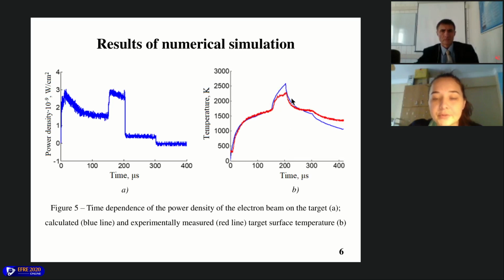There is a difference between the two curves in the peak, which happens because of sputtering of the target during the irradiation by the electron beam. Then you may see the plateau, which relates to crystallization processes happening in the material. And then you may see the difference at the end between the two curves. It is happening because of changes of thermophysical coefficients with the temperature in the surface layer.